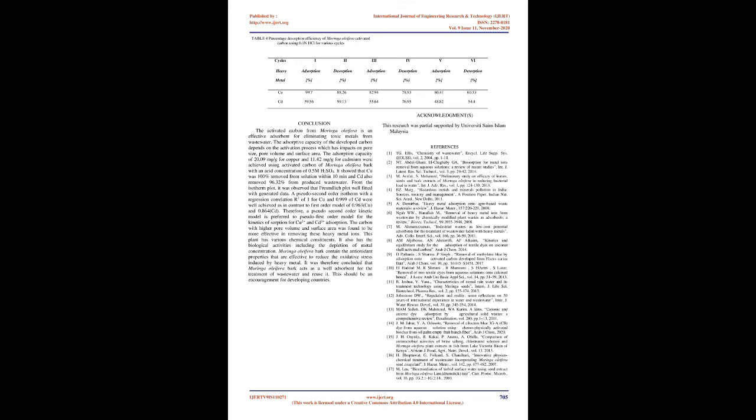At pH 2, the metal adsorption was lower due to the presence of available H+ ions. These H+ ions contested with metal ions for the active sites, hampering the adsorption of Cu2+ and Cd2+ ions onto activated carbon. The protonated active part was not capable of adsorbing metal due to electrostatic repulsion. As the pH increased, H+ ions decreased. Therefore, many negatively charged sites were prepared and metal ion uptake increased by electrostatic attraction.